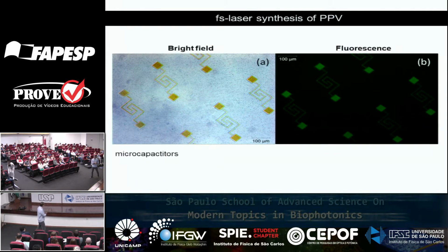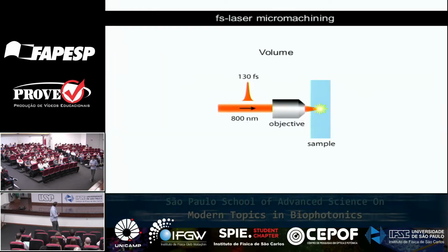So those are sets of microcapacitors that we fabricated using the method that I just described. And here's a fluorescence microscopy image. So you can see, of course, PPV, the yellow thing, is fluorescent. So of course, you can see it fluoresces in the green. And the rest, which is actually the precursor polymer, PTHT, you don't have the fluorescence. So that's another proof that we were able to convert one important polymer in a localized manner.